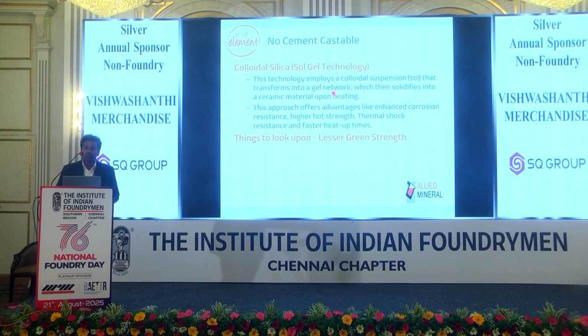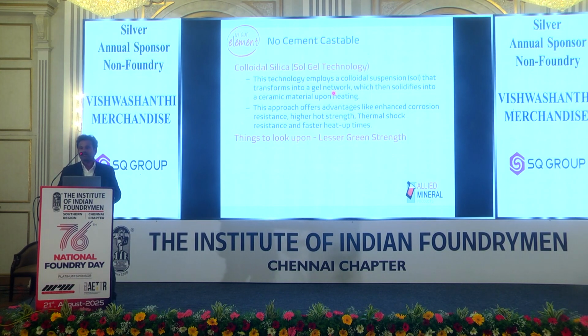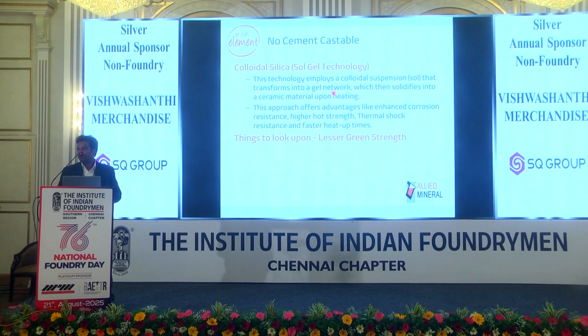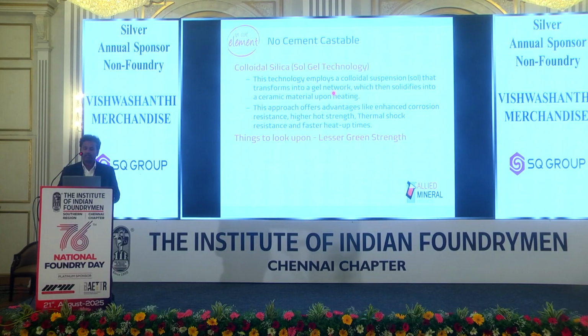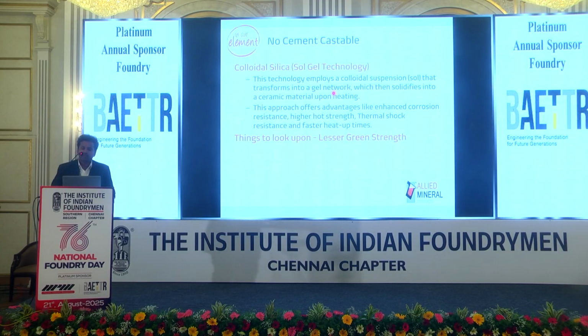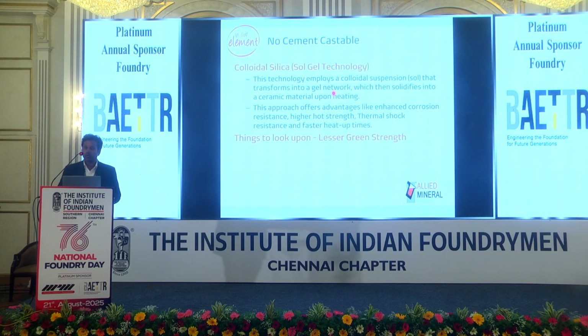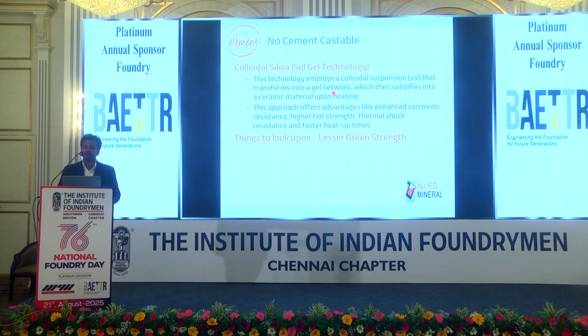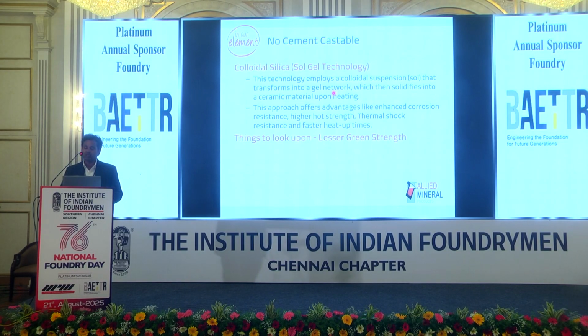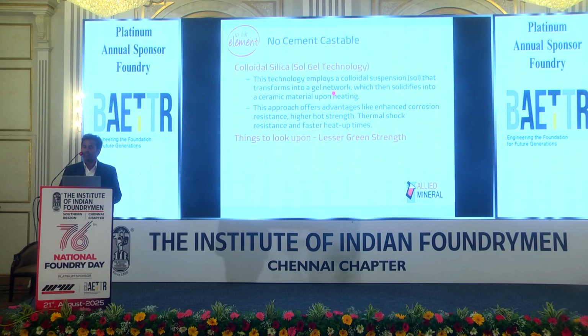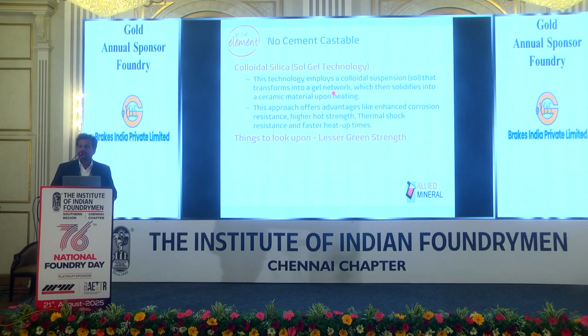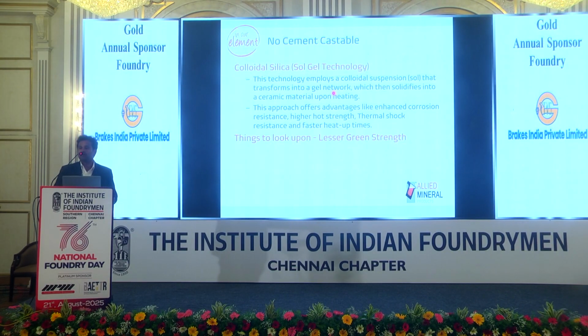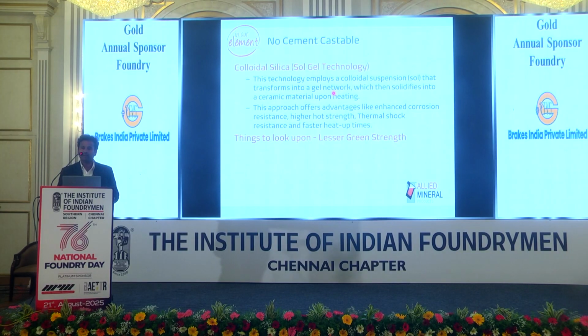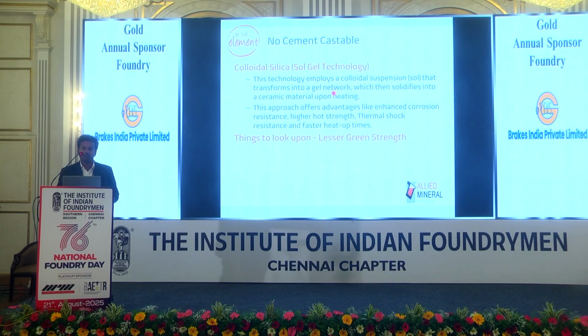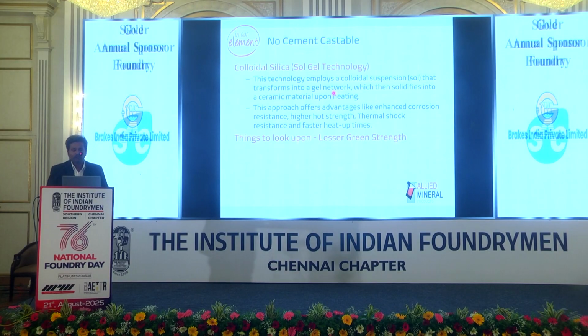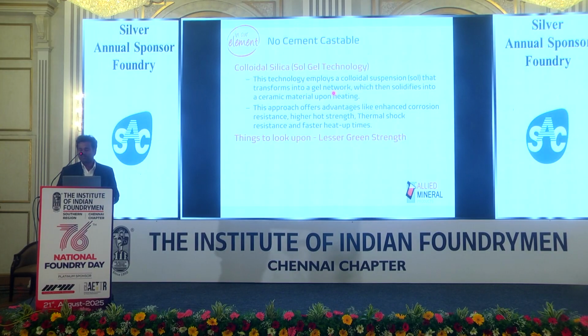Next comes the no cement based castable. It can be either phosphate bonded or colloidal silica technology. This technology employs a colloidal suspension sol, like colloidal silica, that transforms into a gel network, which then solidifies into a ceramic material upon heating. So it has suspended silica particles, at nanometer level, in a solution. Upon heating, it attains the strength.